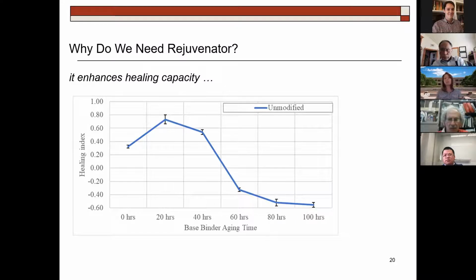Asphalt can have some healing capacity, but over the aging time, up to 100 hours, you can see the healing capacity drops almost to nothing. So it was initially high, but as it aged, it keeps dropping to nothing. So if I wait enough, like I wait 100 hours for this healing to reach this point, I would call that asphalt dead. And I call that the critical aging point. If you wait too long to get to the critical aging point, you don't have a chance to make it alive. Like if I'm dead, you can't bring me back. But if I'm sick, you can make me feel better, right? You can improve it. So the same thing, if the asphalt got sick here, maybe we can help. But if it's dead all the way here, sorry, too late.